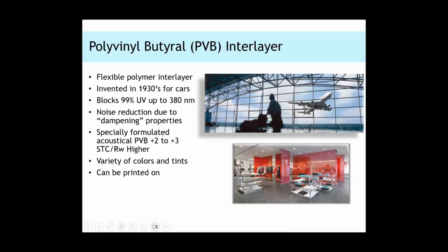The most common interlayer is called polyvinyl butyral, or PVB. It was first invented in the 1930s for automobile vehicles because all that was around then was annealed or float glass, which was causing death and injuries during car accidents. So ever since the 1930s, PVB has been inside the glass of a front windshield. Initially, back in the 1930s, all the glass in the vehicle was laminated with PVB. One advantage of PVB, besides the safety aspect, is it blocks 99% of the UV, so your dashboard and your carpet won't fade.